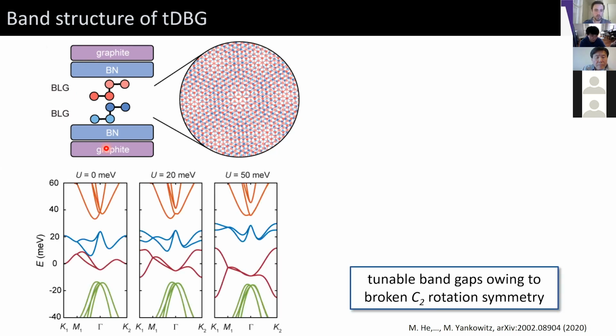Now, we can calculate what we expect these bands to do as a function of the electric field or the interlayer potential U. And it turns out that it's somewhat complicated. So a lot of things change at once when we change the electric field. But here are the salient features. Without an electric field, we have somewhat flat conduction and valence Moiré mini bands separated by an energy gap from the more dispersive remote bands. And these bands actually overlap. So the system is a semi-metal without an electric field.